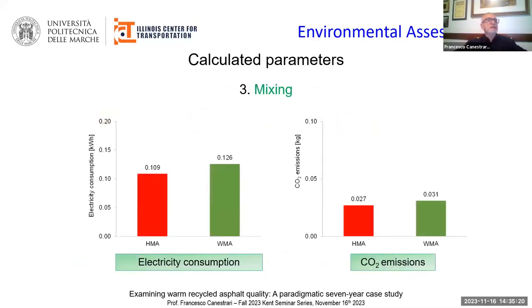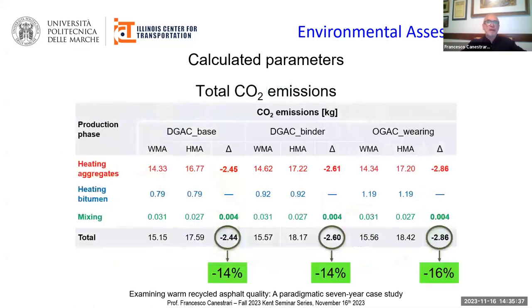In the case of the mixing phase, there is an increase in electricity consumption and CO2 emissions in the case of warm mixtures, because a longer mixing time was assumed for a better wrapping inclusion in the final mixture.